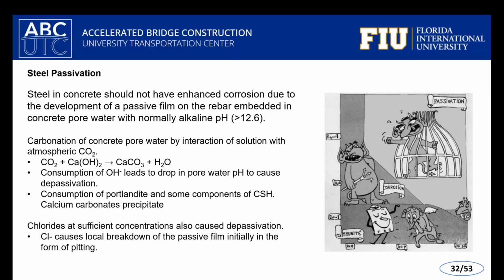In certain environments the cage can break down, the devil is prevalent, and corrosion can occur. The effect of aggressive environments like chlorides really is able to break that devil free from that cage essentially. So we'll talk about some of the material ramifications for chloride penetration, but we'll also spend some time focusing on carbonation-induced corrosion. This has implications for marine bridges, for bridges that have long service lives, and for buildings as well, especially older structures or lower quality concrete. And probably we'll talk about how UHPC can be used to mitigate some of these effects.